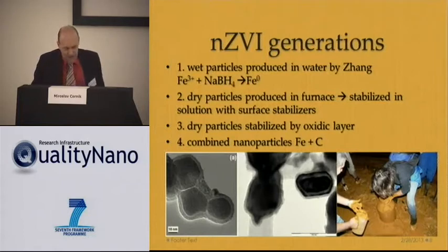This is according to Professor Zhang of Lehigh University, USA. Then the second generation was where particles were produced in a furnace by reduction with hydrogen, and then stabilized with the surface stabilizers I showed before. Then my colleagues from Palacký University came with the idea to protect the surface of the particles by a very thin oxidic layer of the iron and stabilize them later before the application.